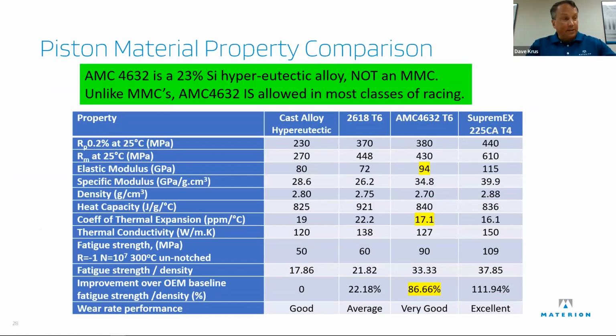So let's talk about this piston material, because I pulled a switcheroo and we got a different piston material in there. It is, as I said, 23% silicon hyper-eutectic. It's made by our powder metallurgy process that distributes the silicon very finely. If you look at the microstructure, and I think that's in the white paper, you'll see that the cast, a 21% cast hyper-eutectic, has blobs of silicon in places where it's a really fine distribution, which is one of the reasons the properties are much better in the 4632.